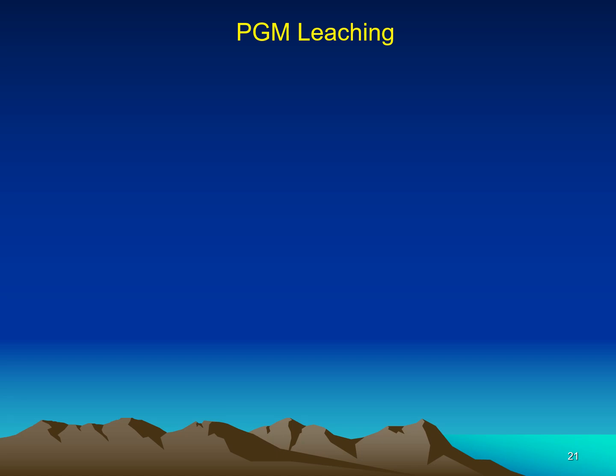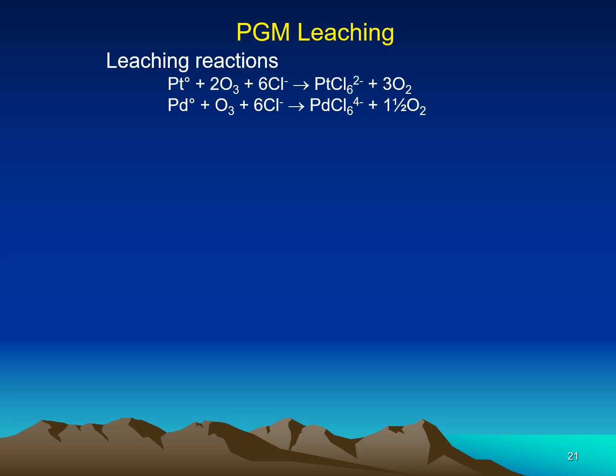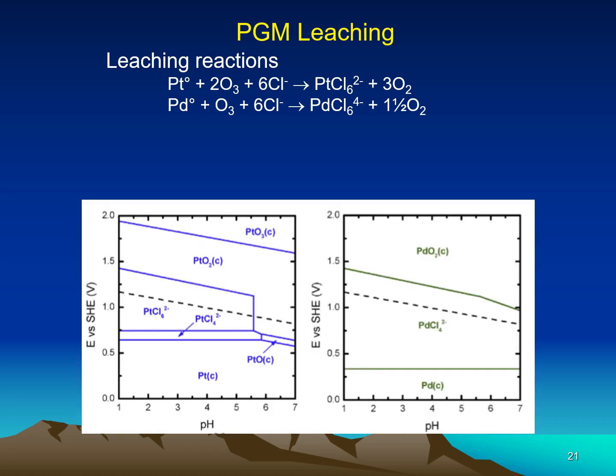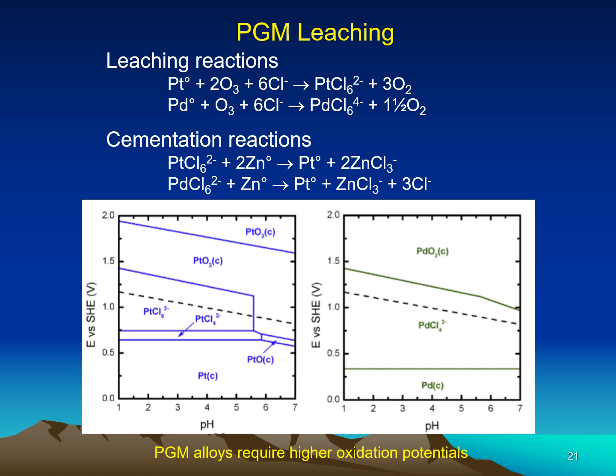Next process that we're introducing is the platinum group metal leaching. And for this particular leach, we need very high potential. So we use ozone in a chloride medium, and this chloride medium is basically salt, sodium chloride, which allows us to use a pH of around 4. The next part of the process would be the cementation reactions, which are very efficient with zinc powder.